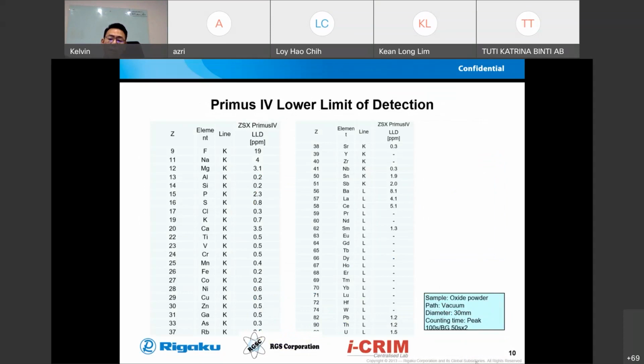So that's why this is an overview of Primus IV lower limit of detection, LLD. This is for the oxide powder, measured in vacuum, with this diameter, counting time, and so on. You can see even for the very, very light elements, from fluorine we can go to 19 ppm. This is for a powder sample. If we are talking about an ultra-trace measurement method, this result can be further improved to ppb level.